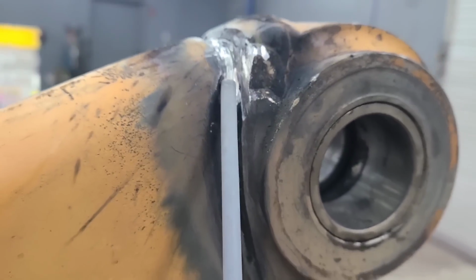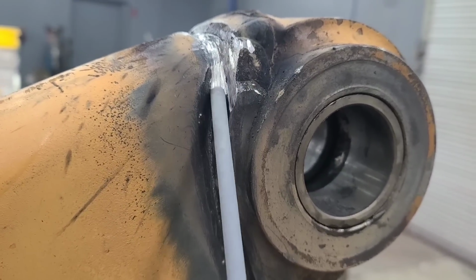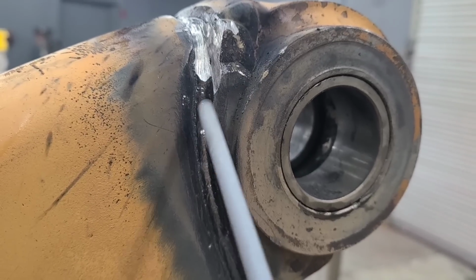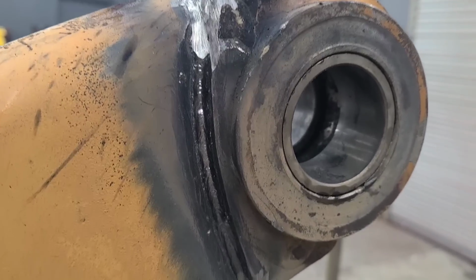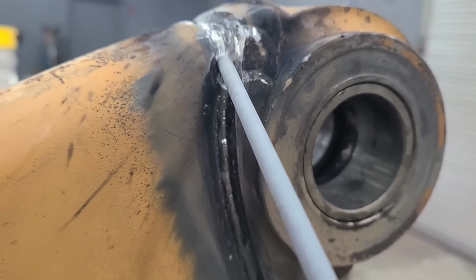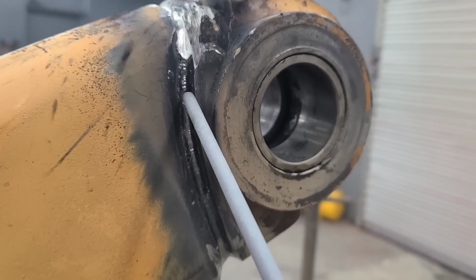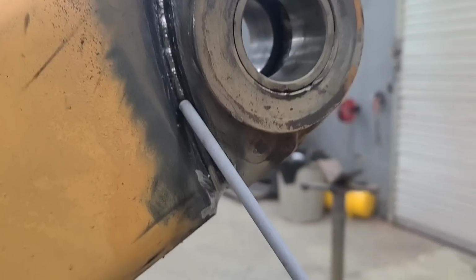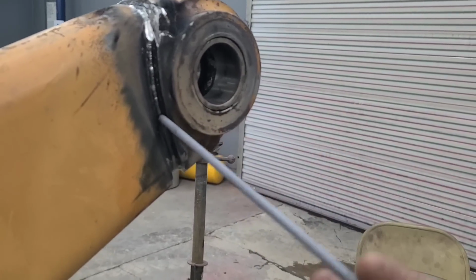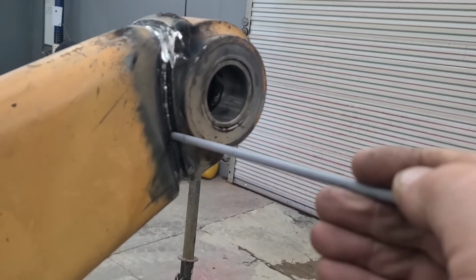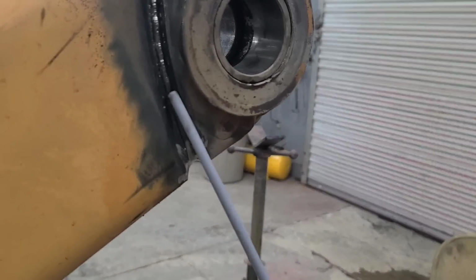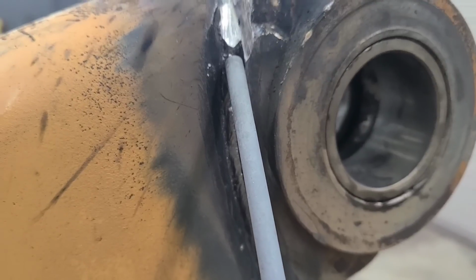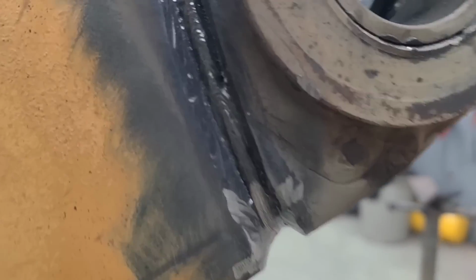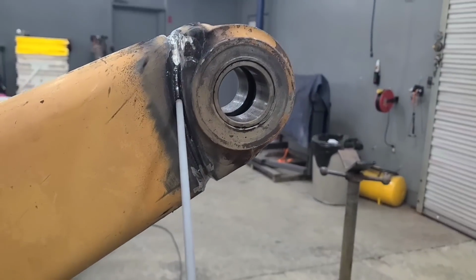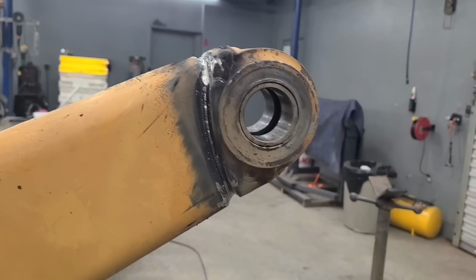Now, if I would have went on scratching after I blew through this, I would have just blown this completely out. Once I blew a hole through it, I knew I had to go into a root bead mode and travel quickly and manage my heat with my rod angle. If I needed more heat, I would raise up. If I needed less heat, I would lay down. And I ended up with this root bead. So you don't want to try to weld over this without grinding.